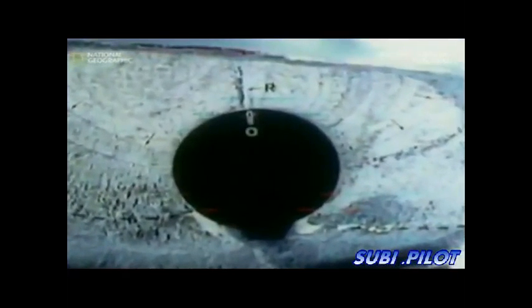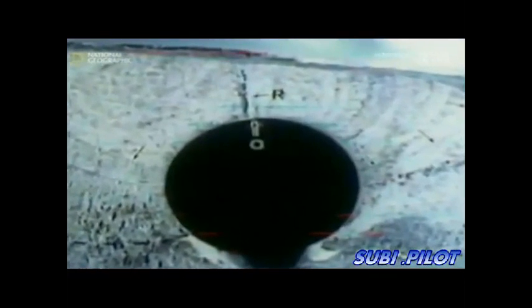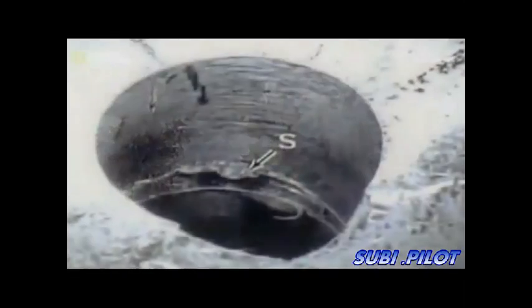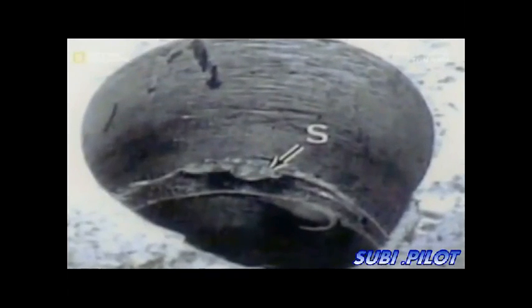Under the microscope, NTSB scientists saw that two cracks along the inner wall of the blade had joined to form a single fissure. This had grown and grown until it circled the blade, at which point it snapped under the stress of normal operation. But the NTSB scientists noted something else. On the inner surface, extending about 4 centimeters from the fracture, there was a series of sanding marks.